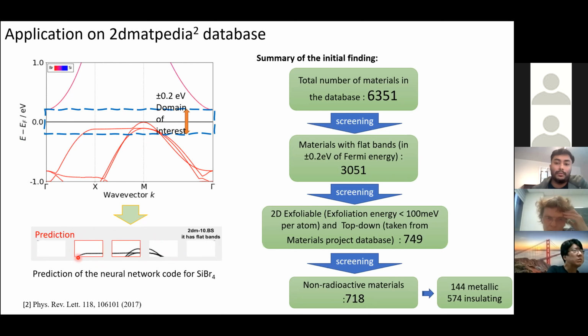So we started with around 6,000 materials in the database, and we end up at around 50% of them having flat bands in that energy range. A flat band is not only a totally flat line; it can start to rise and get flat at some point. That will also pass as a flat band. So that's how we did it.